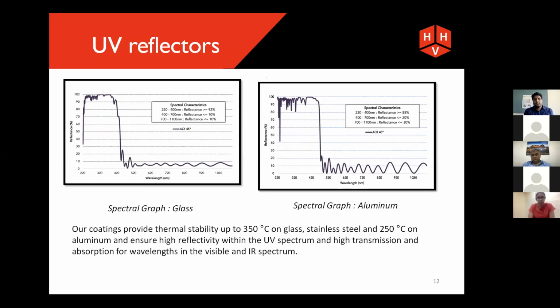You can see the spectral graph on the glass and the aluminum. 220 nanometers to 400 nanometers is getting reflected, and then the remaining light is getting transmitted. These graphs are measured at a 45-degree angle of incidence. That means these reflectors are offering good UV reflection performance at wider angles of incidence.